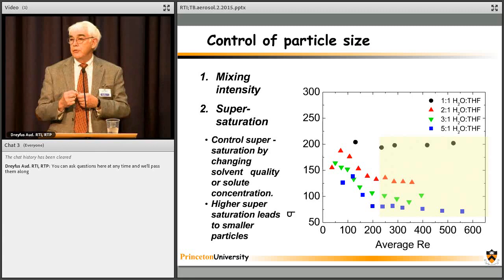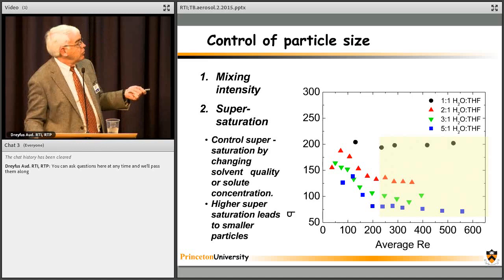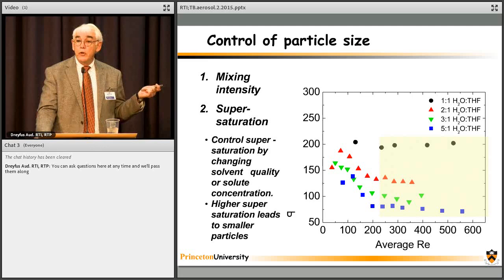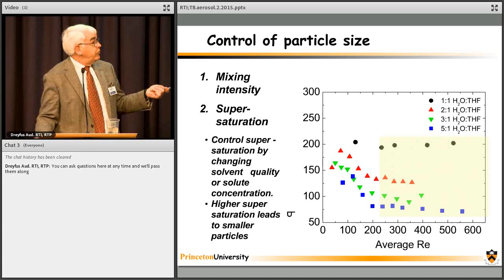So once you're past that, the molecular diffusion is independent of the average velocity in the flow. So for all of these, when I'm above, in this case, a Reynolds number of about 300 for the jet velocities, we make the same particle size. And that's why this process is not really sensitive to the velocity of the jets once you're operating in this region. What do the differences between these four data sets have to do with supersaturation?